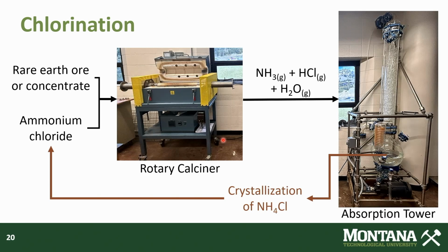Okay, so here's a couple of photographs. The photograph at left, the rotary calciner, is a Thermocraft batch calciner. This is what we've been using to elevate the temperature to about 300, 330 degrees Celsius to get the chemical reaction that we desire to take place. And then actually these two units are close coupled. The two windows, these are the same window, so they're close coupled when we're in operation. So this is where the off-gas reports.